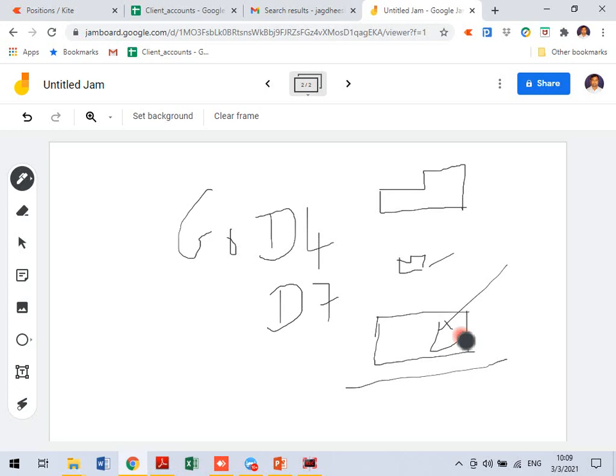Which film has more contrast, D4 or D7? Which subject has more contrast? Because of the thickness difference, simple. If you have more thickness difference, you will have more subject contrast, right? So for example, if I am having it like this, obviously here subject contrast is very high. So this total contrast is called radiographic contrast, which is equal to subject contrast plus film contrast.